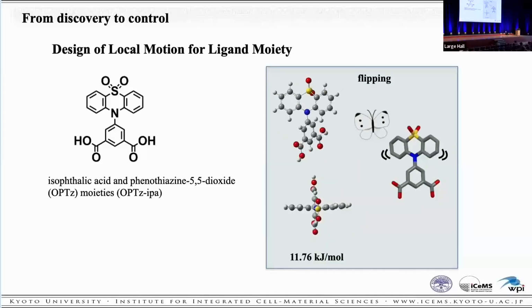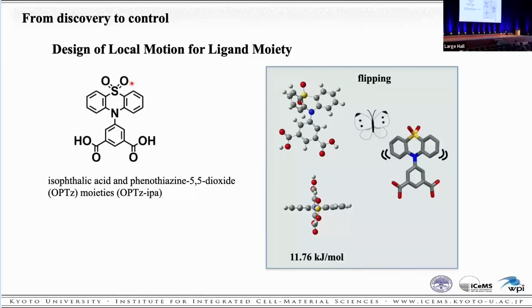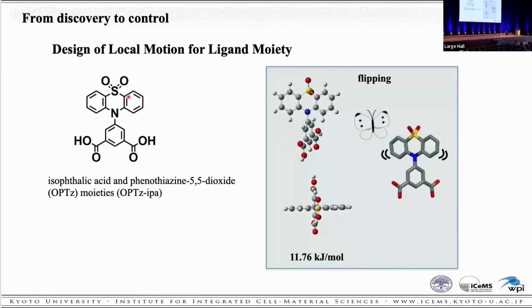We calculated the optimal configuration of the ligand. The ligand adopted a twisted structure with a butterfly shape of the OPTz ring. We calculated the rotation energy of the OPTz ring, and the result revealed that only relatively low energy is needed for rotation.